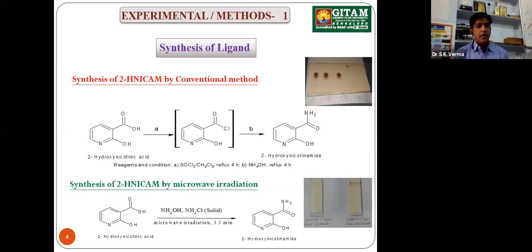This is the synthesis plan for the ligand. We have synthesized it via both methods, the conventional method as well as the green method, that is the microwave irradiation method. We synthesized it using microwave irradiation in the presence of NH4OH and solid NH4Cl, and the duration of microwave irradiation was 3.5 minutes. This ligand, 2-hydroxynicotinamide, was synthesized from its precursor 2-hydroxynicotinic acid.